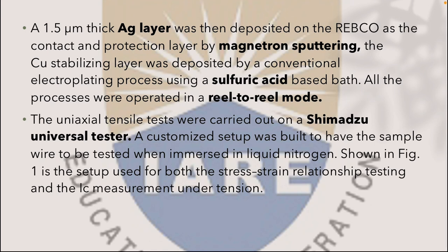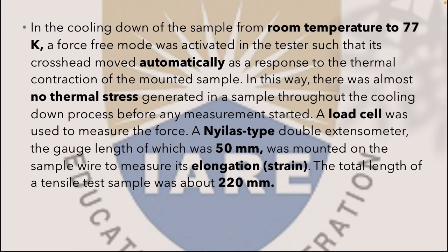Shown in the figure is the setup used for both stress strain relationship testing and the Ic measurement under tension. In cooling down the sample from room temperature to 77 K, a force free mode was activated in the tester such that its crosshead moved automatically in response to the thermal contraction of the mounted sample. In this way, there was almost no thermal stress generated in the sample throughout the cooling down process before any measurement started. A load cell was used to measure the forces. A Nyilas-type double extensometer, the gauge length of which was 50 mm, was mounted on the sample wire to measure its elongation strain.